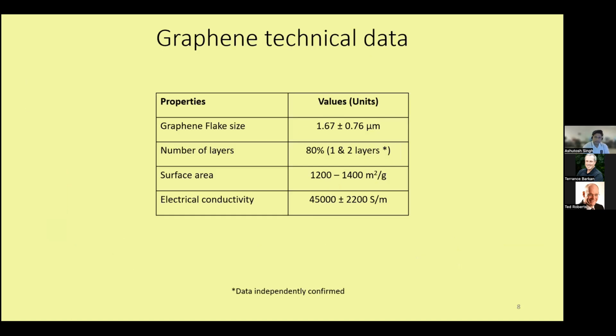In terms of technical parameters, our lateral size was 1.67 micrometer, and 80% of our flakes, highly dispersed in water, were 1 to 2 layers. Because of that, we get a really high surface area. The surface area we measured was 1,200 to 1,400 square meters per gram. We also observed that the electrical conductivity of these flakes was really high. Although we do oxygen functionalization, we do not completely oxidize the graphene. I just wanted to clarify that.